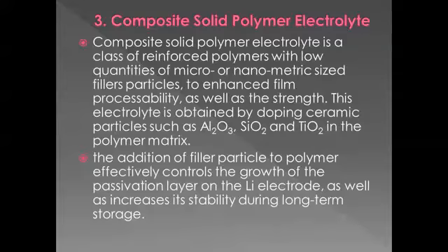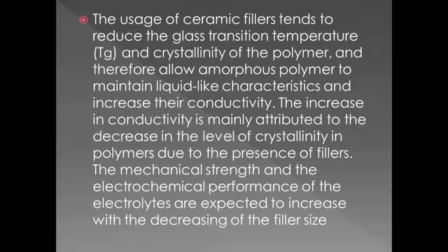the polymer matrix. The addition of filler particles to the polymer effectively controls the growth of the passivation layer on the lithium electrode as well as increases its stability during long time storage. The use of ceramic filler tends to reduce the glass transition temperature and the crystallinity of the polymer, and therefore allows the amorphous polymer to maintain liquid-like characteristics and increase its conductivity.